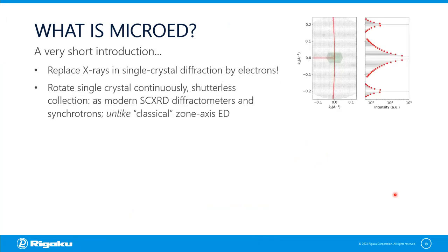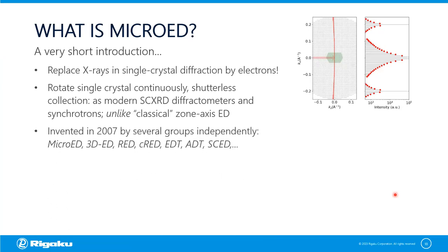So what is micro-ED? In the micro-ED experiment, we're replacing X-rays in the single crystal diffraction experiment with electrons. We rotate the crystal continuously, just like we do in the shutterless X-ray diffraction experiment. And it's unlike classical zone axis electron diffraction, where you line up the sample and you're just looking at a particular zone. This technique was developed by several groups independently in 2007. It's been called micro-ED, 3D-ED, RED, and so on. The most common terms these days are micro-ED and 3D-ED.